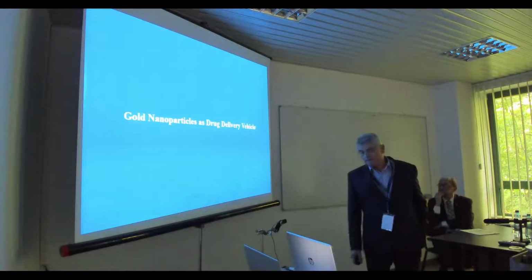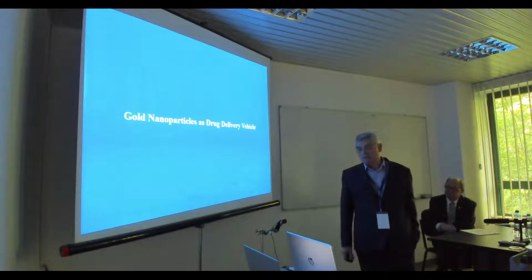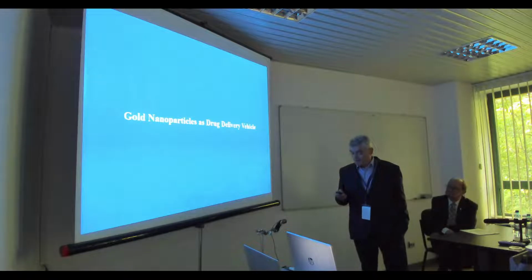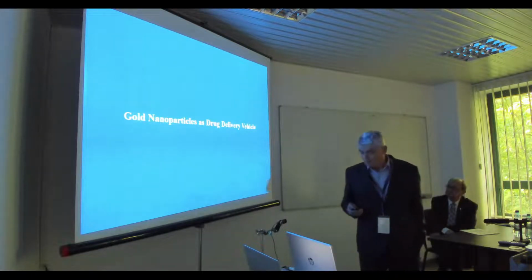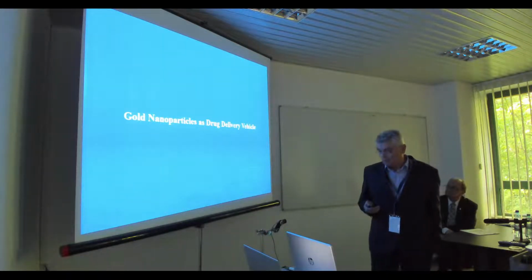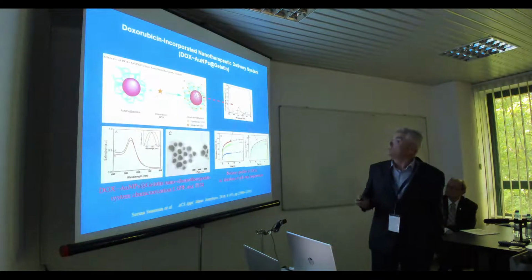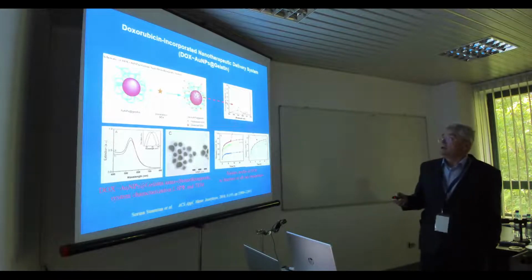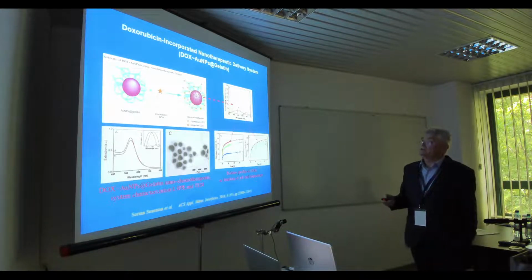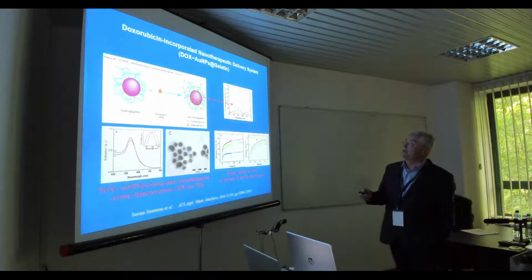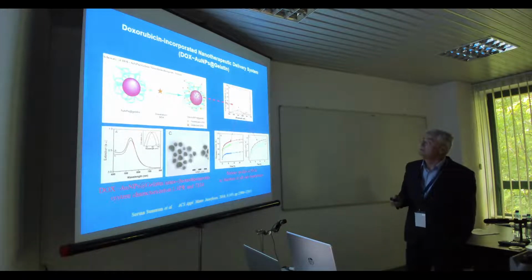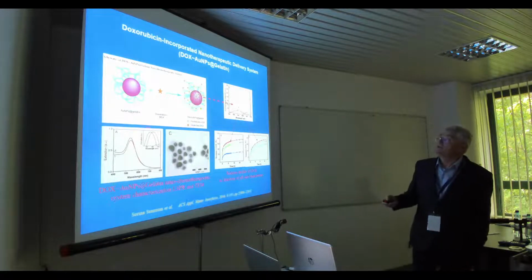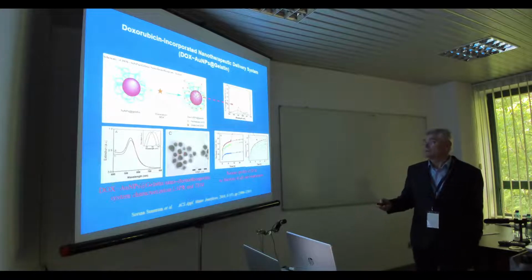Now, you can use a nanoparticle also as a vehicle to deliver a drug. One of our studies concerned delivery of doxorubicin, which is a chemotherapeutic drug. The procedure was to capture this doxorubicin in the polymer shell of the nanoparticle; the shell was gelatin.